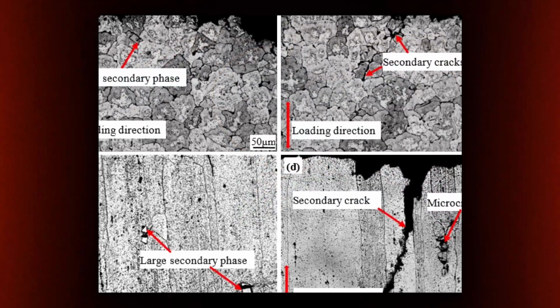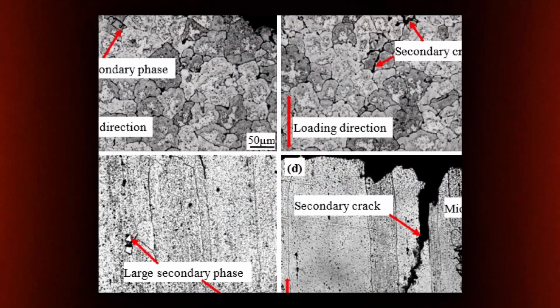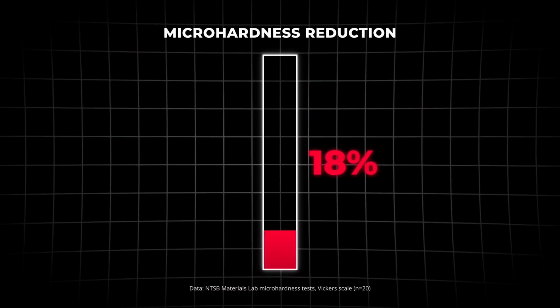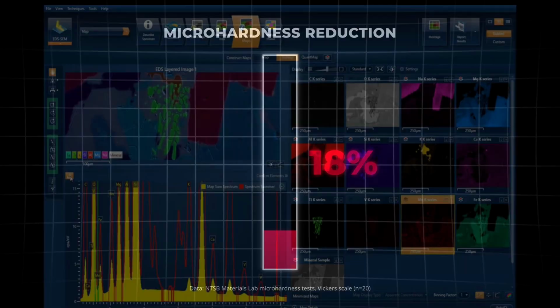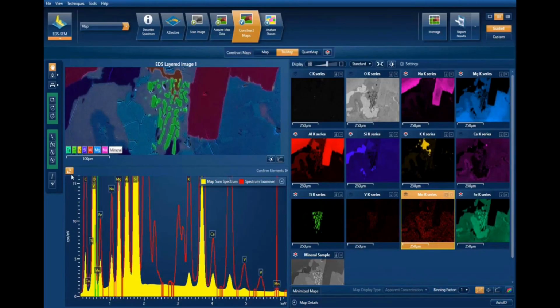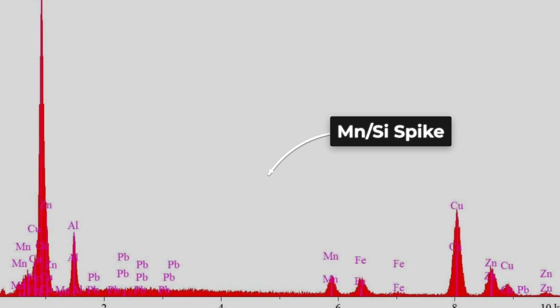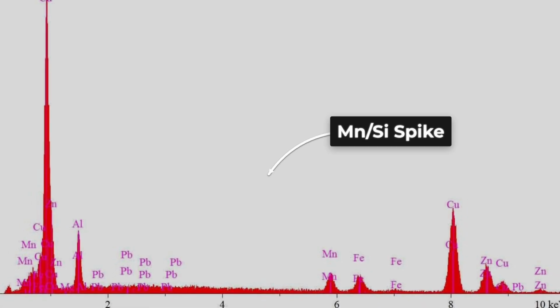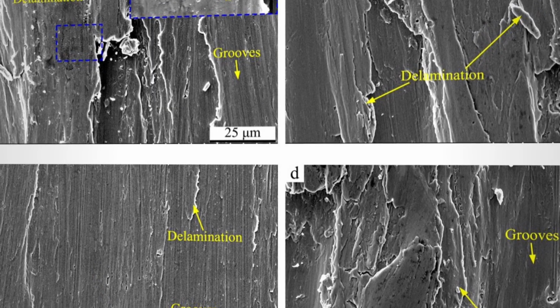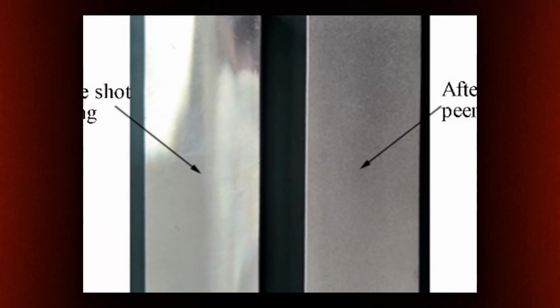Annotated images highlighted a zone of altered microstructure at the crack's root. Here, the metal was 18% softer than the surrounding alloy, a result confirmed by microhardness testing. The EDS spectra told a subtler tale: a spike in manganese and silicon, just above baseline, hinting at contamination from a past repair. The surface bore the telltale dimples of shot peening, a protective treatment meant to shield against fatigue. But on this fitting, the peening was uneven, overlapped in some places, absent in others.